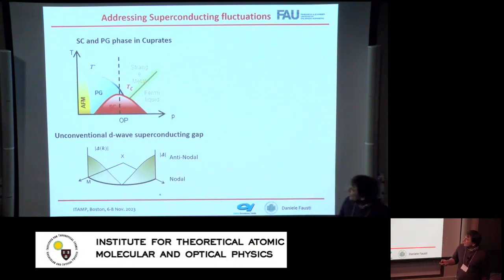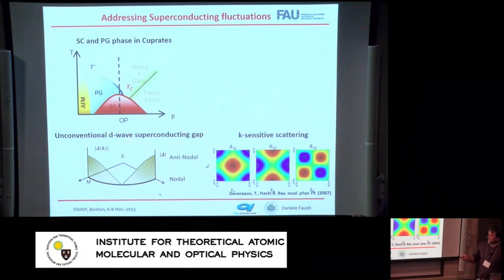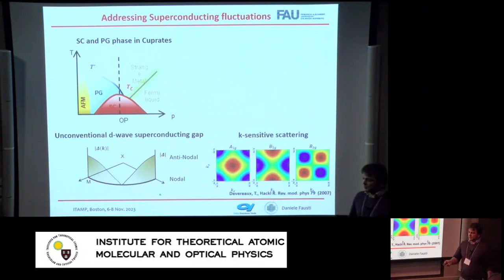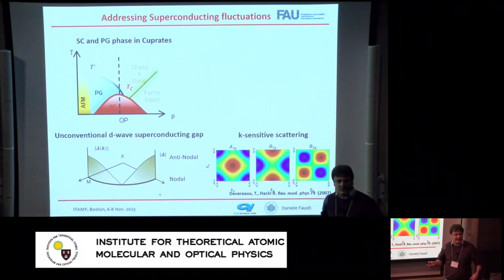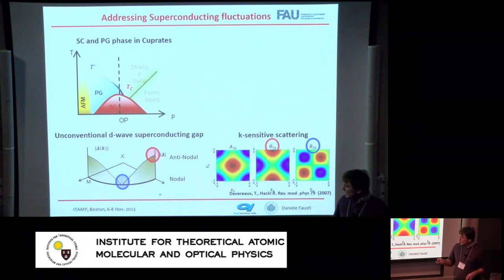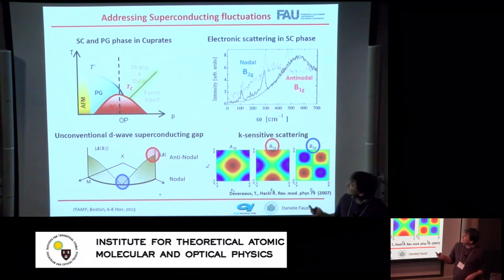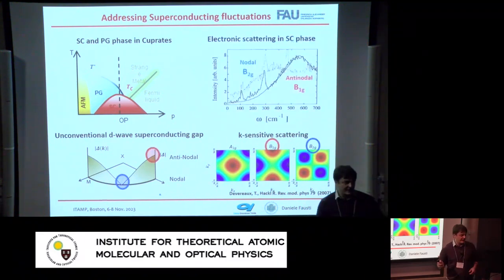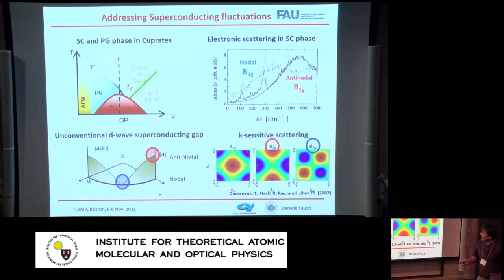But essentially, in cuprates, you are sensitive to electronic Raman scattering from the superconducting level, and it's well known in the literature that if you select different configurations, essentially you can be sensitive to electronic Raman scattering associated to nodal or anti-nodal excitations. So that's one almost 15 years old reference. But essentially, I want to be very procedural here. So there is a broad electronic scattering which is associated to the onset of a superconducting state.